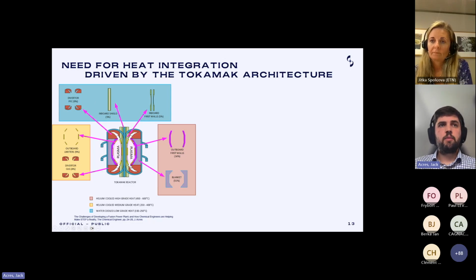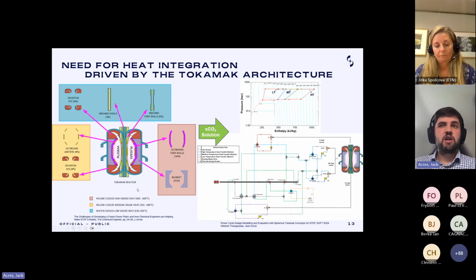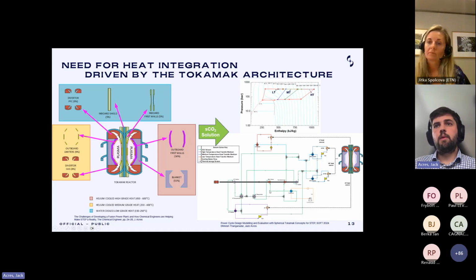So this presents a bit of an issue in terms of heat integration, trying to integrate all of these different types of heats from these different components into a single cycle is challenging, especially with incumbent technology. So what's quite nice about the recompressed Brayton cycle in particular is that you can start manipulating the enthalpy gap within that cycle to integrate these different grades of heat. So for example, by adding the low temperature grade heat as a bypass to your recompressor.